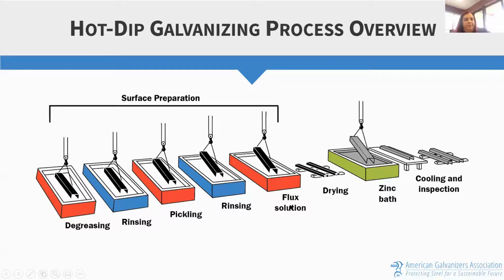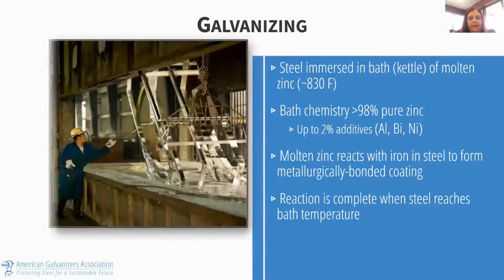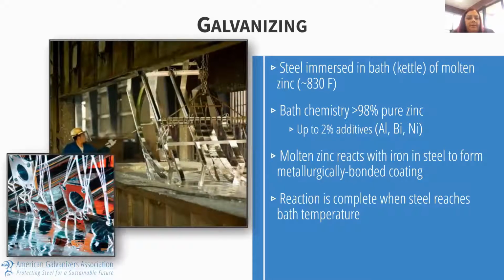And then the final step of the surface prep is a flux solution, which will do any final mild cleaning of contaminants on the surface since it was removed from the pickling bath. And more importantly, put a protective layer on the surface so no contaminants will form before going into the galvanizing bath itself.